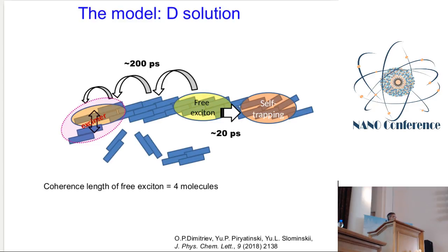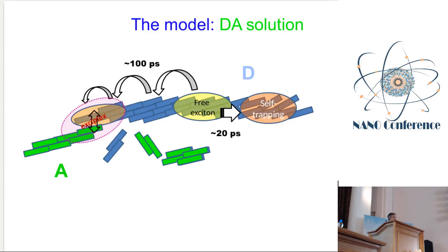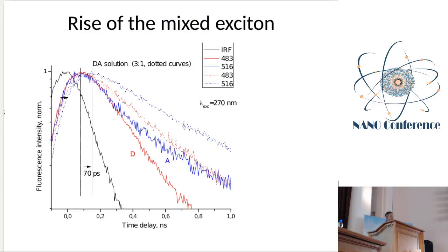This exciplex formation is also accompanied by the rise. In order to form the exciplex, the exciton should have some time for the diffusion to the specific sites. And we really observed this rise time, which was about 70 picoseconds.